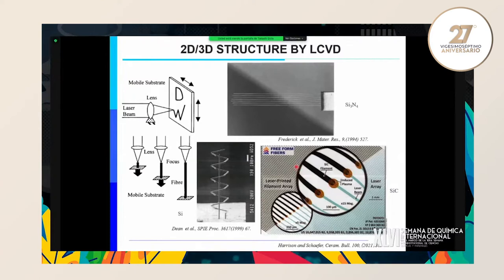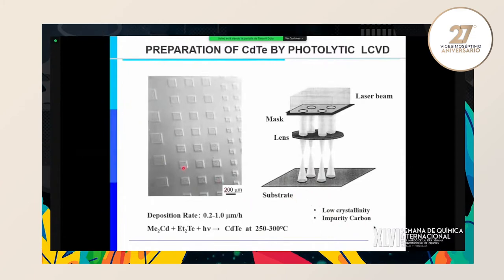Laser CVD has been used in the past to make very thin dots, filaments, nanodots, very small materials only by focusing the laser. In the past, everybody used laser focusing to make small materials. Laser CVD is also used to make very thin films. This is called photolytic laser CVD, where the laser is used for photochemical reactions. This is used to prepare films with almost no heating of the substrate. The laser itself can decompose the precursor gas and deposition proceeds. Of course, it gives very low crystallinity and contains impurity carbon, because metal organic compound precursors contain a large amount of carbon. So laser CVD has never prepared very big bulky material in the past.